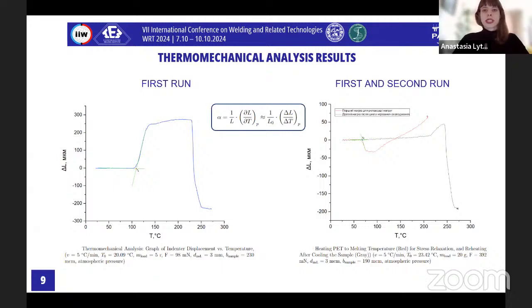The coefficients of thermal expansion obtained through this method vary, as the material with internal stress, like shown on the left graph, tends to exhibit a lower coefficient of thermal expansion. Of course, this is because some of the energy applied during heating is used to overcome these stresses, and once these internal stresses are relieved, restrictions on atomic movement in the crystalline lattice are removed, and it allows the material to expand more freely in response to temperature changes. So this method can effectively describe the thermomechanical characteristics of a part printed from filament, as PET goes through the same stages during filament production.